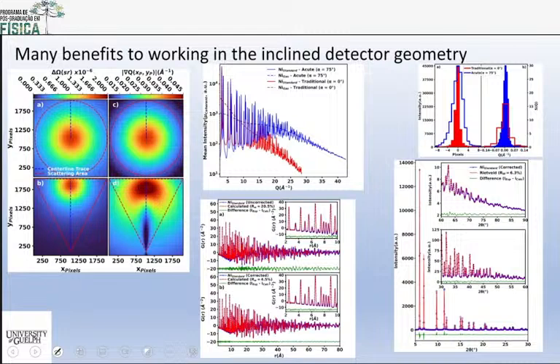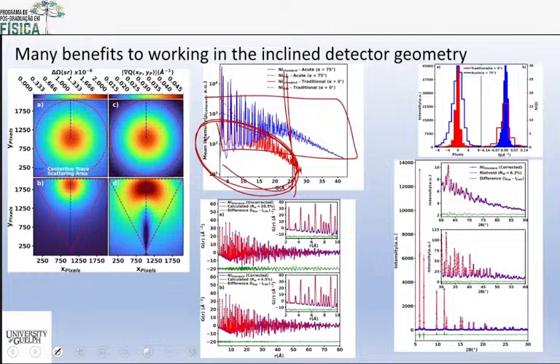So here we published a paper where this is the intensity pattern. You see what I'm drawing? This is how the intensity is spread over a regular detector, while ours is spread in a very different pattern. So our intensity stays up high, even out to very high momentum transfer. So most people can't go beyond 20, 25 inverse angstroms. We can go out to 40. What's that important for? Because the higher you go out in Q, the better your resolution.